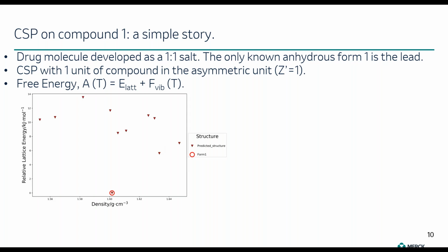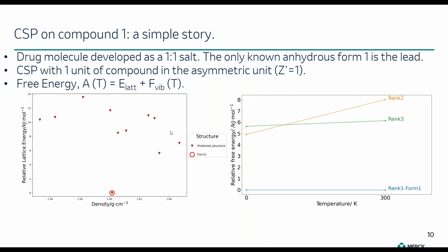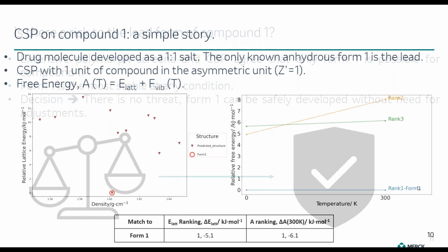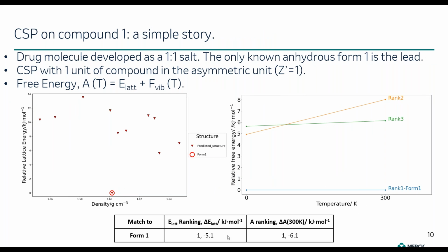So the outcome was that in lattice energy, a match to form 1 was the global minimum, the lowest energy predicted crystal structure, by quite a wide margin relative to any of its competitors. And when we went into free energy calculations at finite temperature, we saw that this form remained the most stable even at room temperature, 300 Kelvin. And you can see here that the gap relative to its competitors increased from 5 kilojoules per mole in lattice energy to 6 kilojoules per mole in free energy at room temperature.